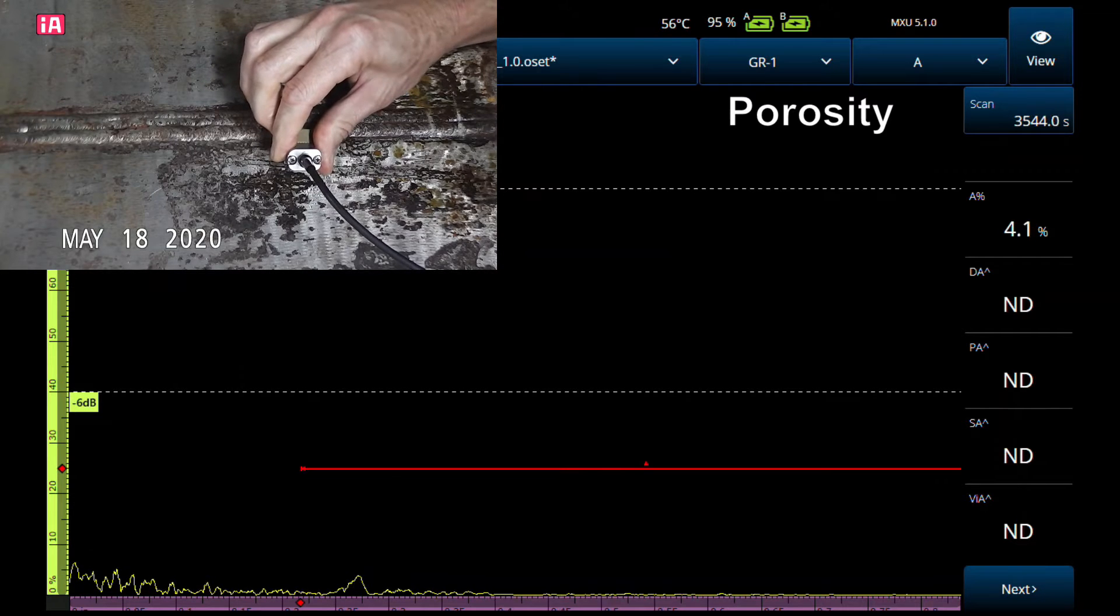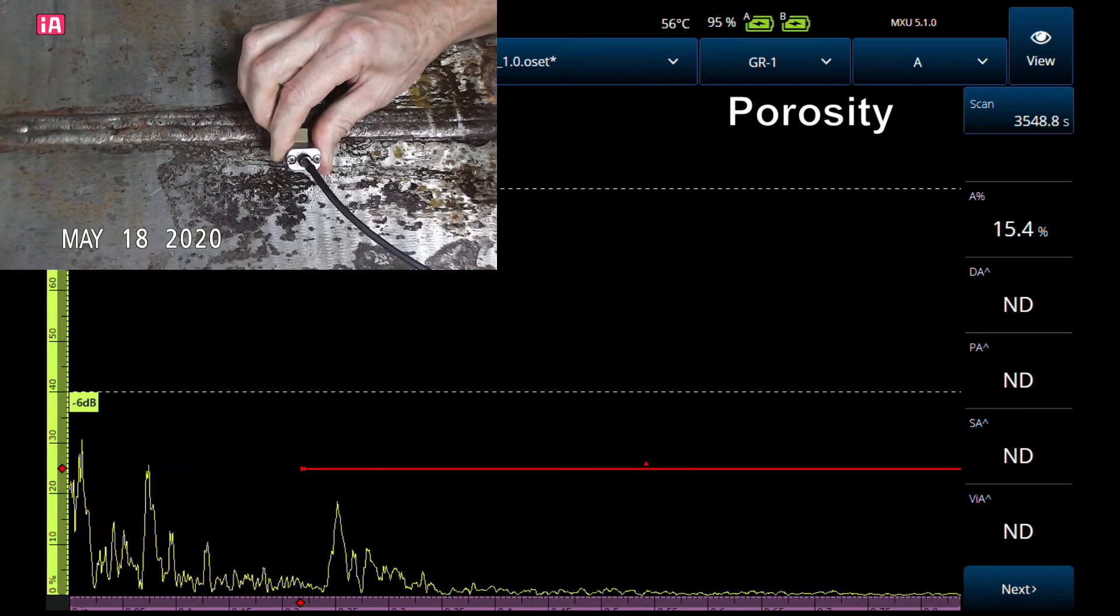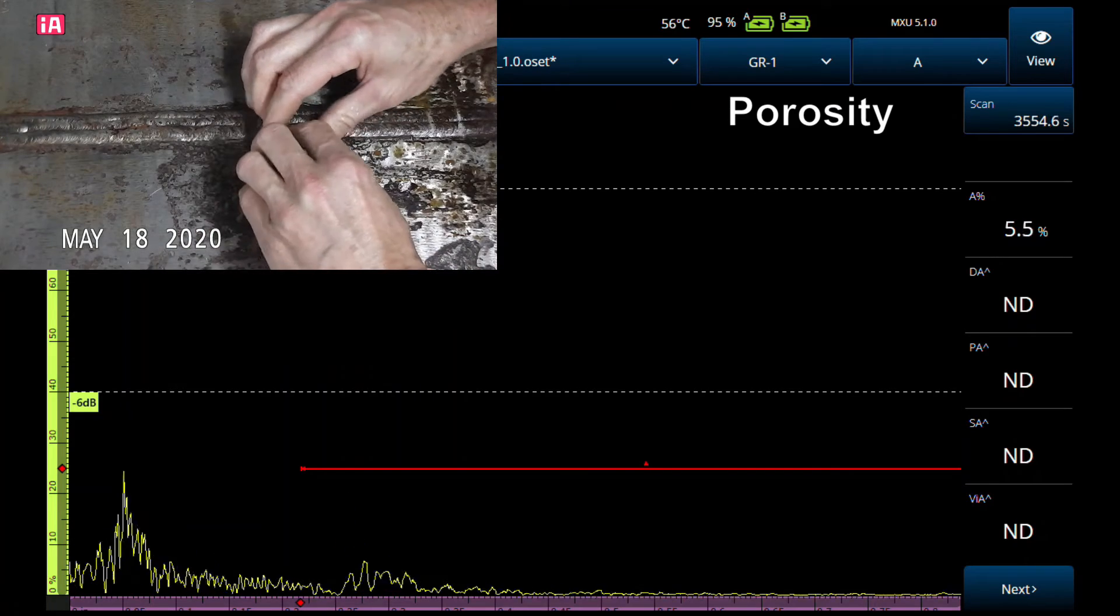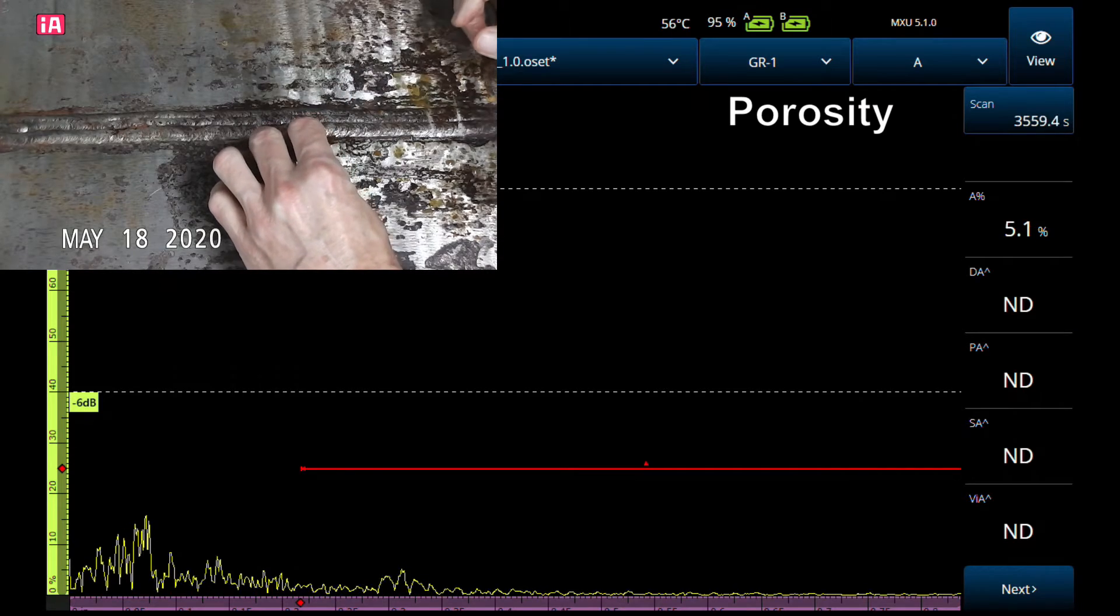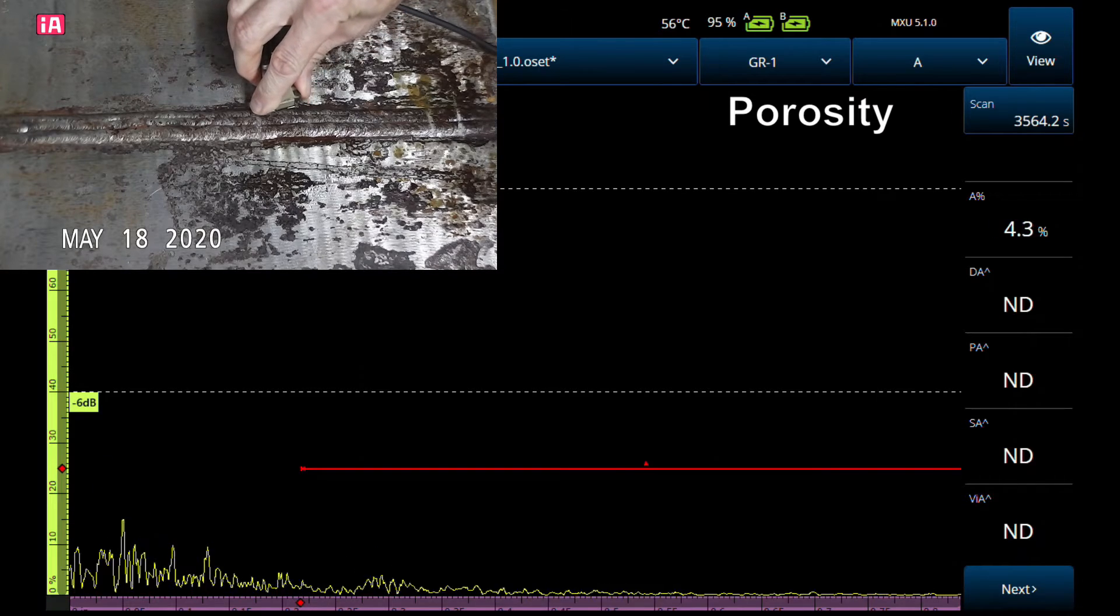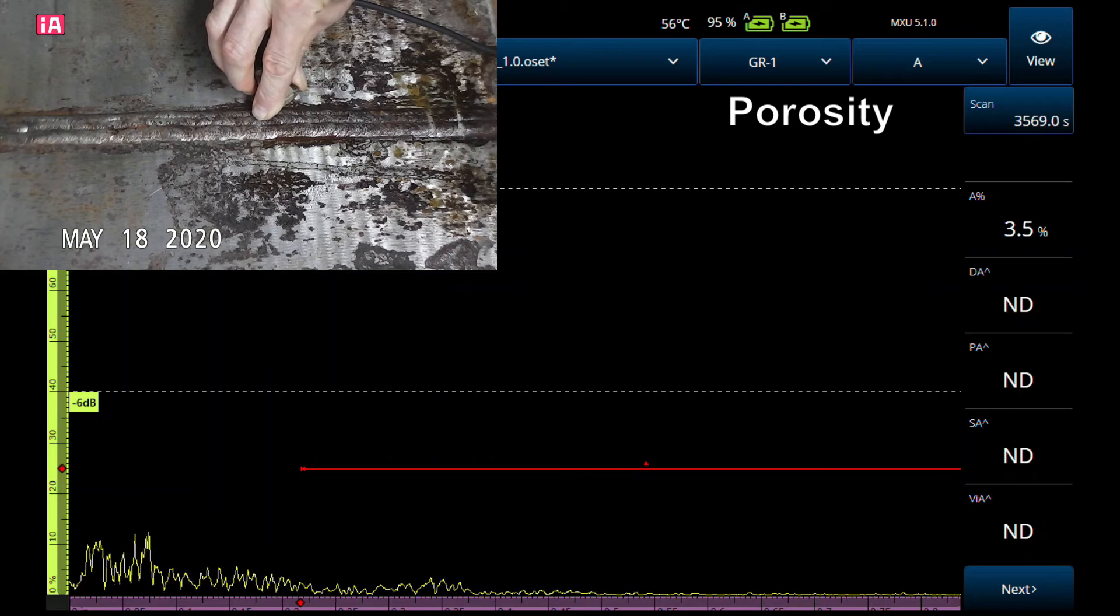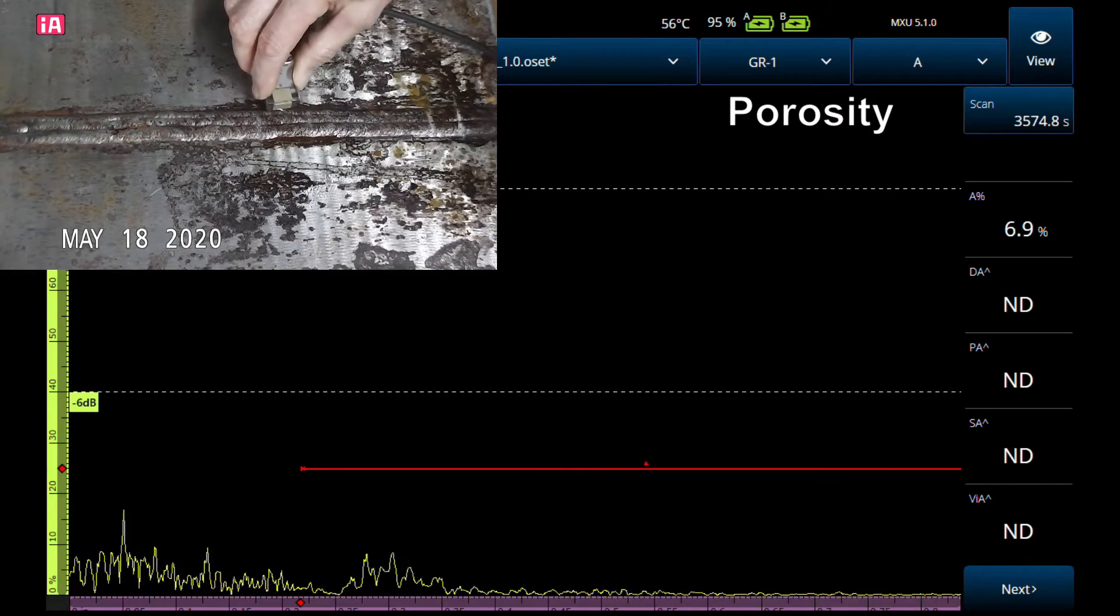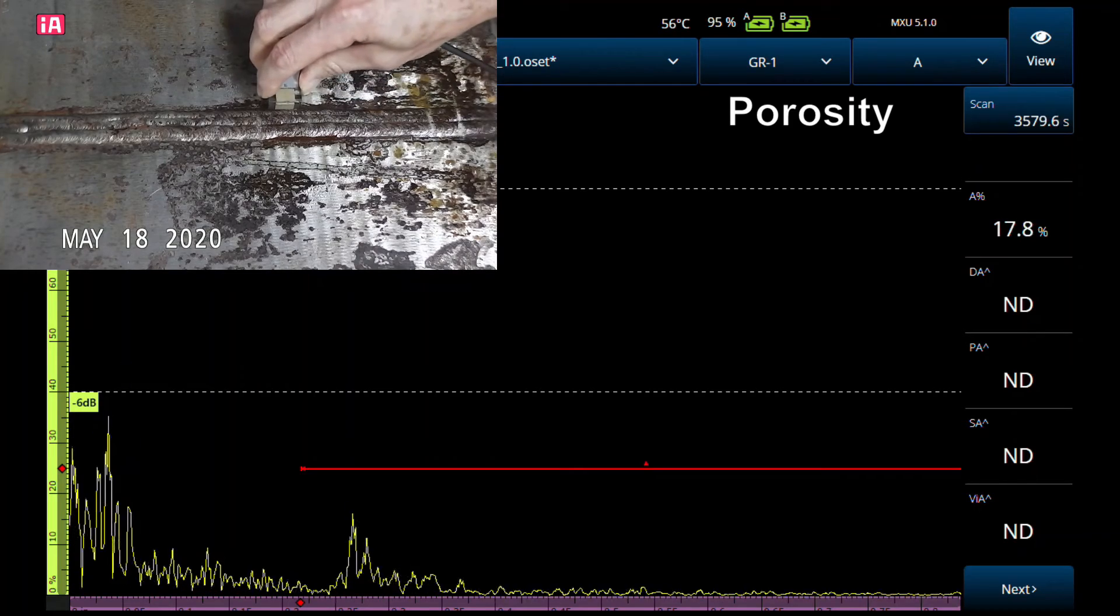Very low in amplitude. Let's put it back up to plus 12. Now watch what happens when I skew the probe—how much I can skew it and still see the signal there. It's still on the screen and look how much that is. Let's go to the other side. Still have the signal. Look how far that probe is skewed. And that is porosity.